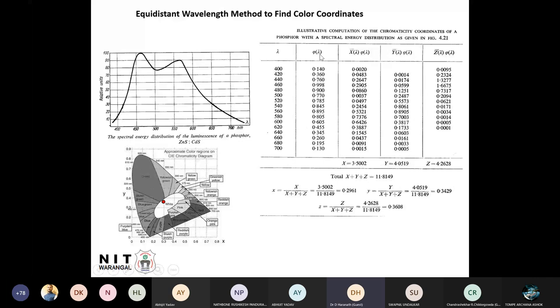This is one of the famous methods of finding these coordinates, called the equidistant wavelength method, but there are many other methods also available. If you take the summation of this one, it is treated as capital X. The summation of this one, just the addition, is Y. The addition of this one gives Z. So the total is X plus Y plus Z. The x coordinate is capital X divided by X plus Y plus Z, which gives 0.29. And y is equal to capital Y divided by X plus Y plus Z, which is 0.34. Z we don't need here, but you can calculate it.